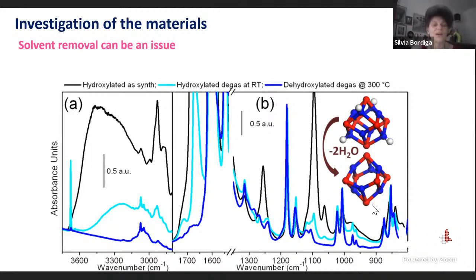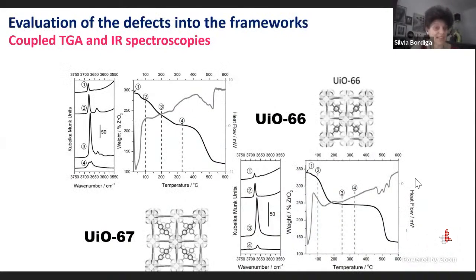This is a nice example where, in the case of a MOF based on zirconium with the zirconium cluster, we move from the sample as made, which is reported with the black curve, upon activation, so trying to remove the solvent. We observe that already at room temperature, a large portion of the solvent is removed. And activating at a mild temperature of 300 degrees, we are able to remove all the solvent, so water, and also DMF, which is used for the synthesis. And so we are able to obtain an empty material where we can play with the chemistry. However, this is not always the case.